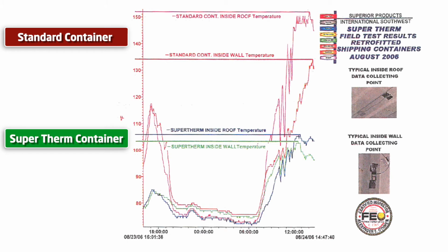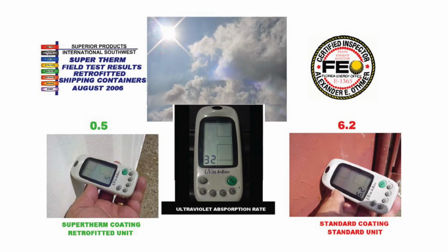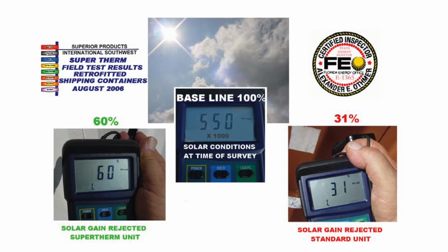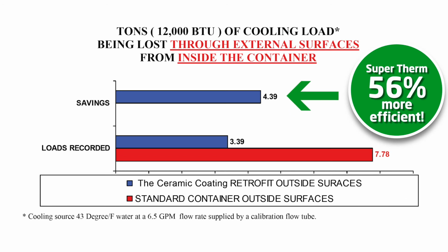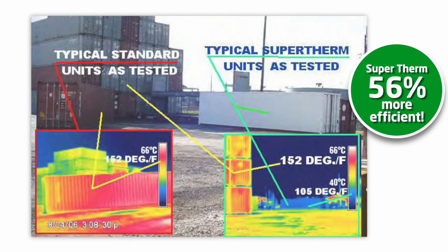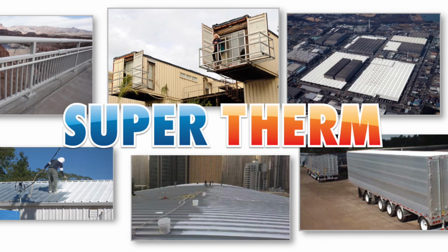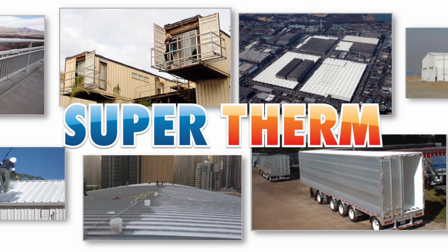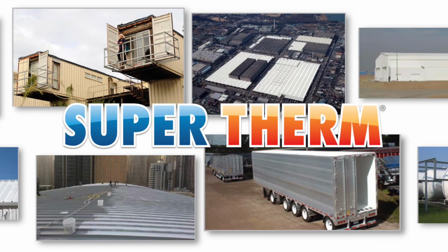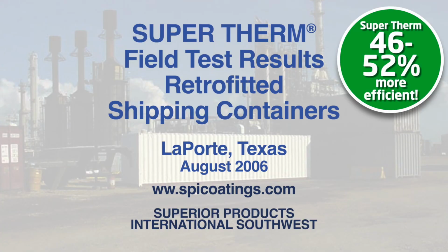What's the bottom line? In this particular instance, over a 24-hour period, we analyzed over 4,320 independent data points. Regardless of whether we were looking at external surface temperatures, internal compartment temperatures, internal humidity, external reflectivity, or ultraviolet degradation, the container retrofitted with the Super Therm coating was 46 to 52% more efficient than the standard containers.